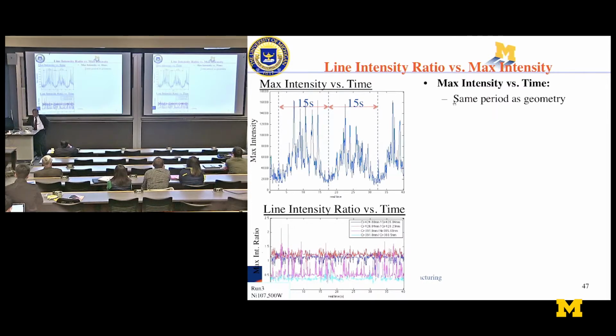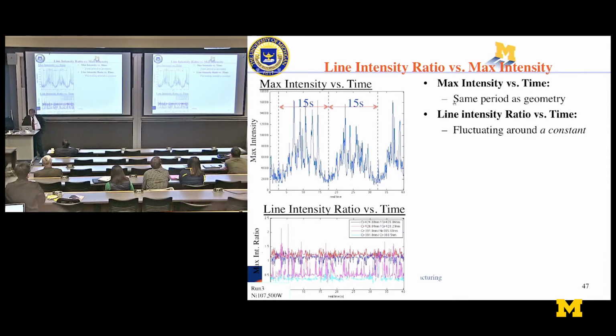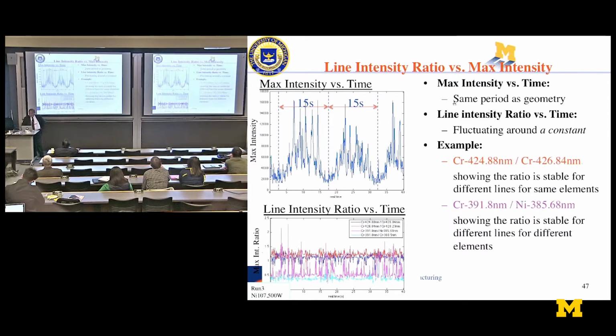So with this, the fluctuation can be basically normalized. One of the examples is using these two lines. We show that the bottom line is line intensity ratio is independent of the fluctuation. So we found a way to make this online observation more stable. But once you have that, human beings are greedy.